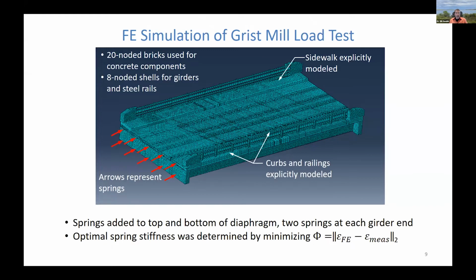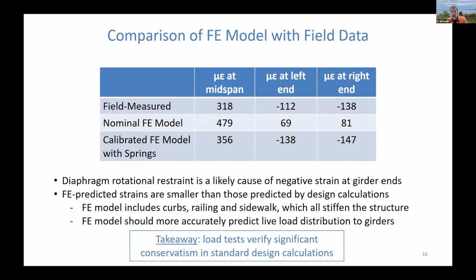And then we went through and we determined through a minimization procedure what that spring stiffness was. We minimized the difference between the measured strains and the model predicted strain. So this is a calibration process, a tuning process. We don't know what the stiffness of those springs should be. But indeed, if we go through that exercise, you can see from the first and third rows in this table that we can pretty closely match what we measured in the field. And that gives us more confidence that that rotational restraint from that end diaphragm is a likely cause of the negative strain at the girder ends, i.e. that partial rotational restraint of the girder ends.